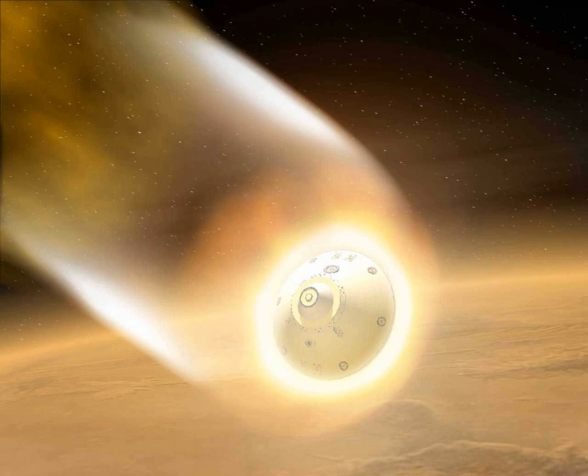This outcome is prevented by ejecting the heat shield with its heat soak prior to the heat conducting to the inner wall. Typical space shuttle TPS tiles LI-900 have remarkable thermal protection properties. An LI-900 tile exposed to a temperature of 1000 K on one side will remain merely warm to the touch on the other side. However, they are relatively brittle and break easily, and cannot survive in-flight rain.